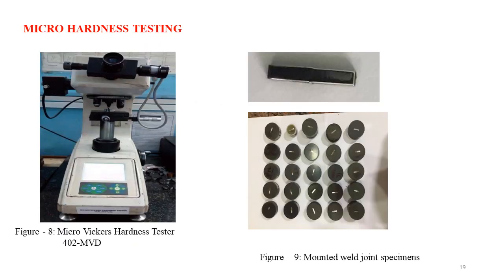Micro hardness measurement. These are the Vickers hardness measurements, measuring hardness at the cross section of the weld zone. That's why the specimens are hard mounted here.